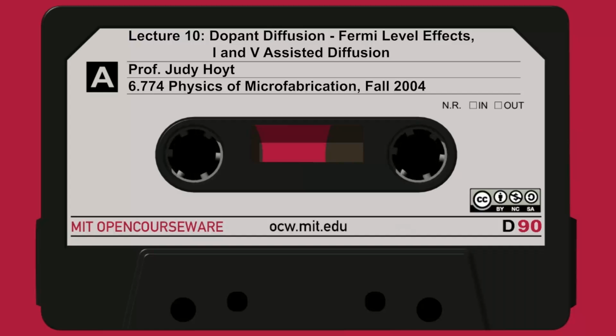Then D_A is just the sum of two terms: the diffusivity of the paired species Ai plus the diffusivity of the paired species Av. And I can break this down even further, where I write the diffusivity of the paired Ai as a little d, the diffusivity of Ai, times the concentration of these Ai pairs divided by C_A, plus a comparable analogous expression for vacancies.